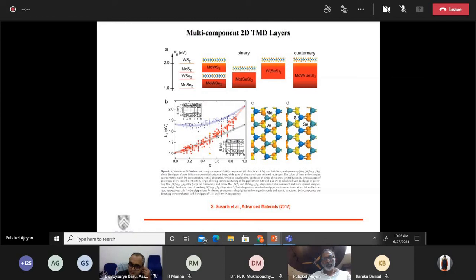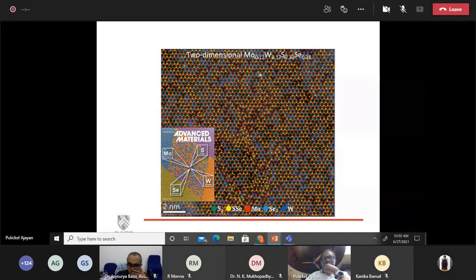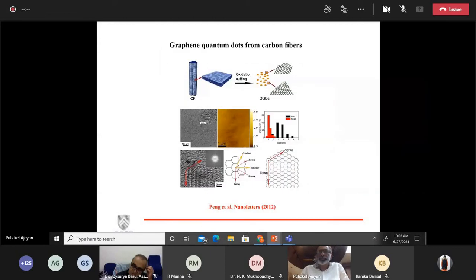And again, we have done quite a bit of these alloying of various types of elements and going to quaternary systems. And here is actually a nice image that shows these alloys in 2D of molybdenum, tungsten, sulfur, selenium. And this is actually an energy filtered image taken by the Oak Ridge group from a sample that we created, showing a very good distribution of these elements in this 2D layer. And we are now pursuing properties of some of these materials, for example, catalysis and electronic property of these layers.